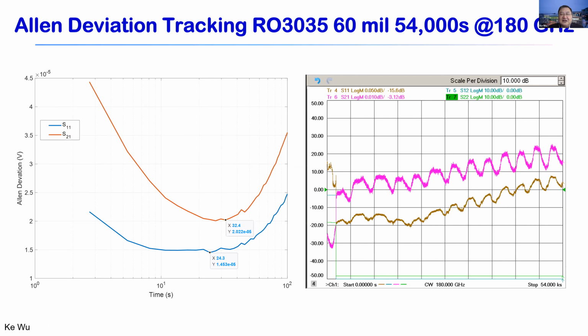We also developed a technique to do so-called Allan deviation tracking. Allan deviation tracking means that we set up a time frame, let the measurement run, and look at the statistical data and the deviation values. This deviation value comes from the statistical Allan formula, and this gave us a certain kind of assurance, particularly for high precision measurements. Usually this is used for atomic clocks, but for atomic clocks over time we talk about years, with deviations in picoseconds or those kinds of values. But here we use Allan deviation to look at measurement value variation over seconds.